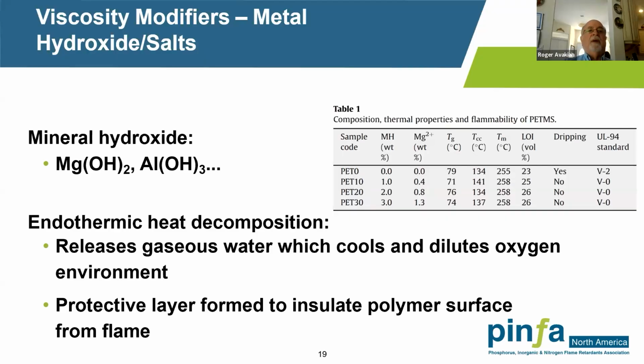Again, we talked about the metal hydroxides or inorganic hydrates like magnesium hydroxide, aluminum trihydrate. And again, as I mentioned before, when we're talking about the mechanisms of flame retardants, these materials undergo an endothermic decomposition in the presence of heat, and they do that at different temperatures, typically magnesium hydroxide at a higher temperature than aluminum trihydrate. And they release gaseous water steam at that temperature, which cools the flame and also tends to dilute the amount of oxygen that's available for the fire. So again, that fire triangle is working in two areas there.